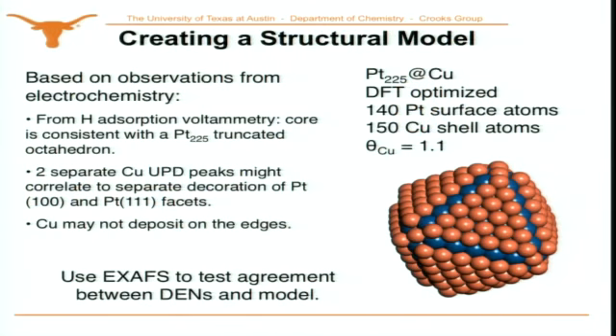This is the same truncated octahedron that we were just looking at. It has, of course, 140 platinum surface atoms. That's the normal number of surface atoms in this particle in that outer shell. And now what we'll do is just decorate the facets with copper atoms. We'll close pack, but only on the facets, and we'll leave the edges exposed. And that turns out to take 150 copper atoms rather than 230 on the previous slide.